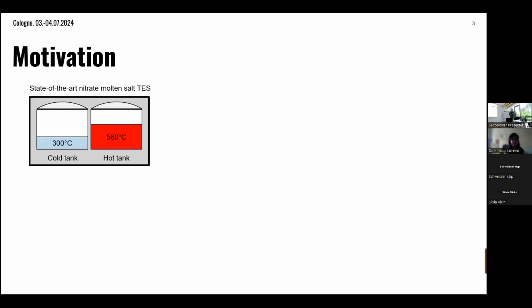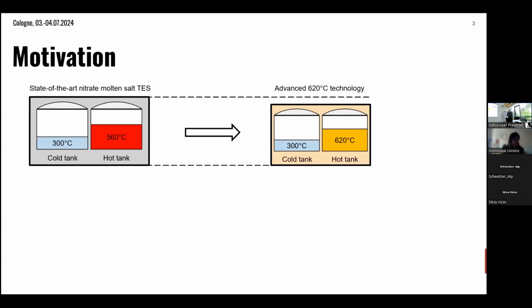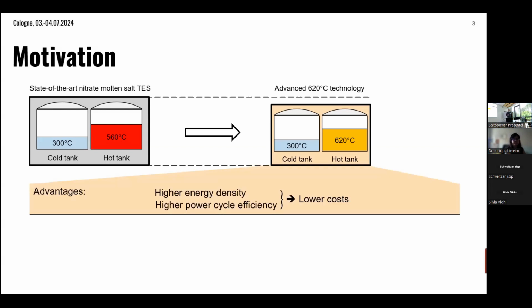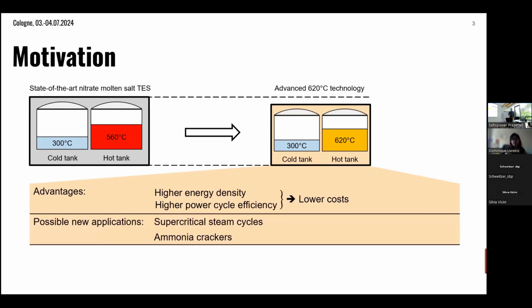As you all know, the state-of-the-art temperature limit for nitrate molten salt storage is 560 degrees. Usually we have a two-tank system, and the idea is to increase the temperature of the hot tank. In this way, we have several advantages. One is that we have a higher energy density, and the other is that we can also achieve higher power cycle efficiency. This leads to overall lower cost.